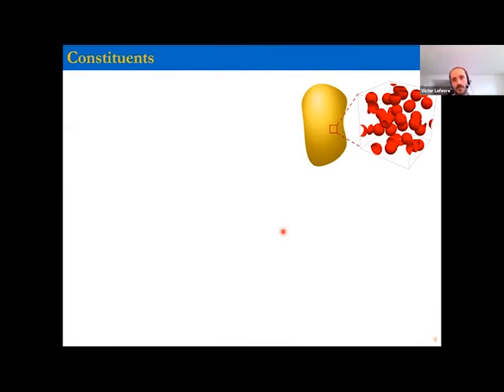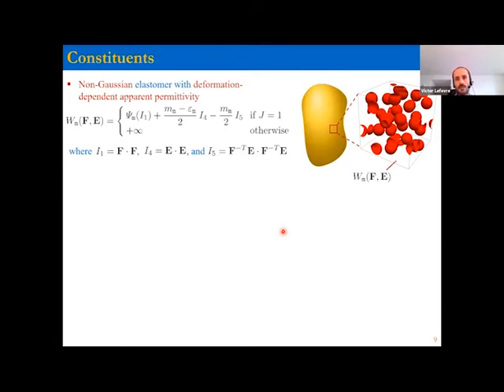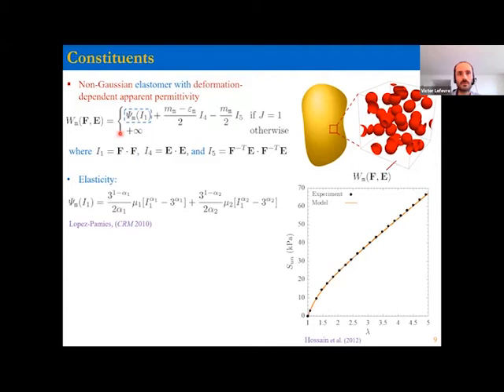So before talking about the solutions, let's talk about the constituents. So for the matrix, we're going to take that it's a non-Gaussian elastomer with an apparent permittivity that may depend on the deformation. That corresponds to this choice of free energy function W m. There are two parts to this function. The first one is this function psi m of the first invariant that describes the elasticity of the elastomer. It could be any function of the first invariant. It could be Neo-Hookean, the Gent model, the Arruda-Boyce model. We're going to use this model here.